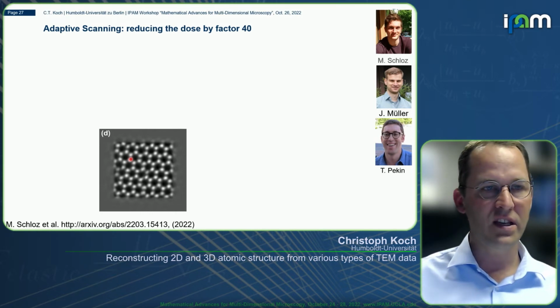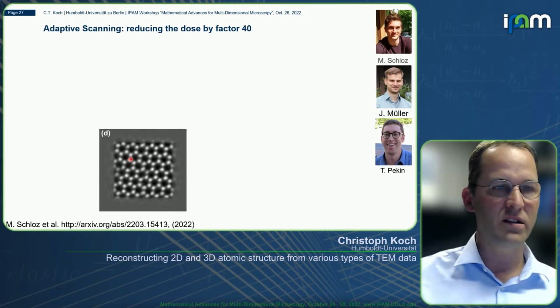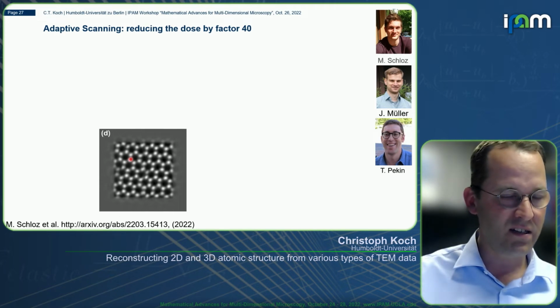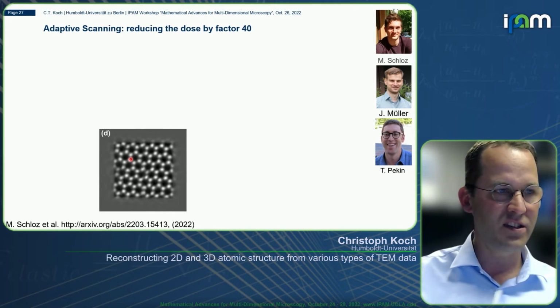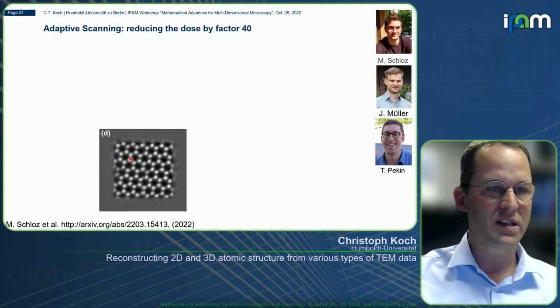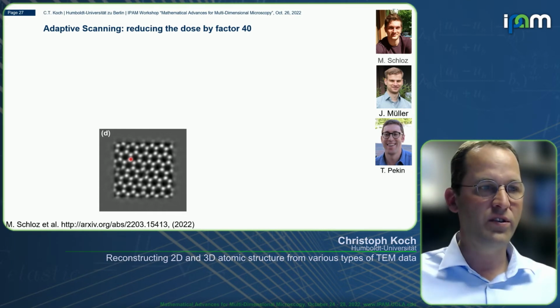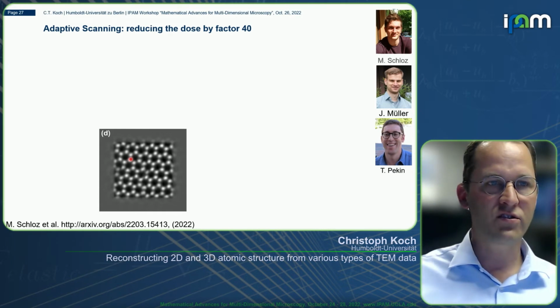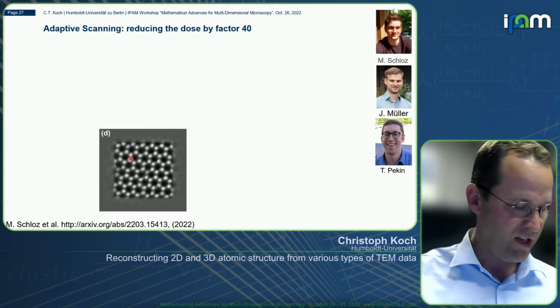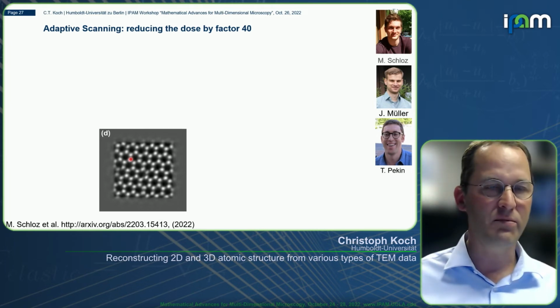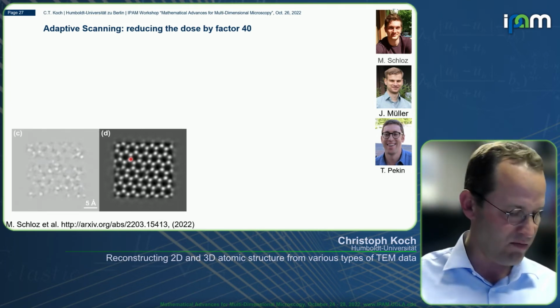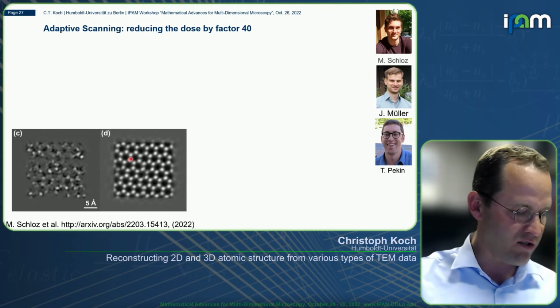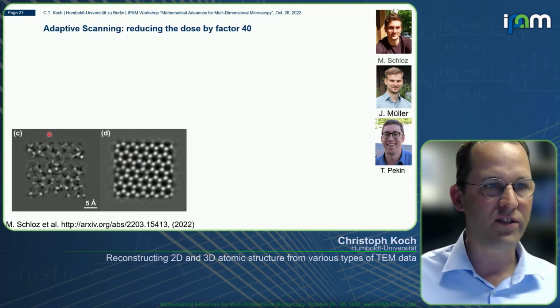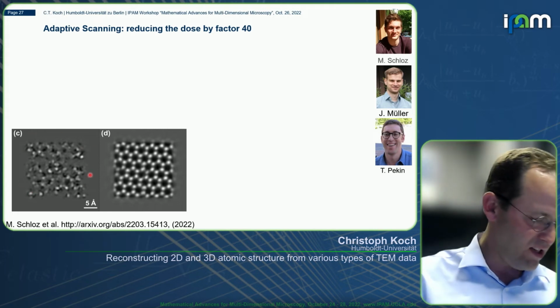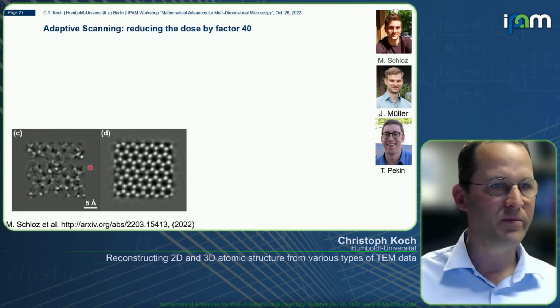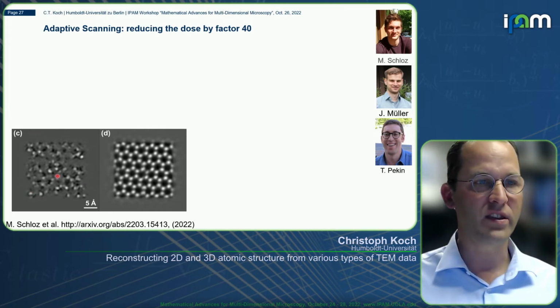The first thing that came to our mind was that we could do an interlaced scanning, but then you hit the atoms in a regular way, which gives some moiré-like wave pattern with your atomic structure. So let's just try random scan positions. If you do that, like we would in some compressed sensing schemes, and do a reconstruction of only 1/40th of the beam positions, you don't see all the atoms very well anymore. The question is, can you improve on this?